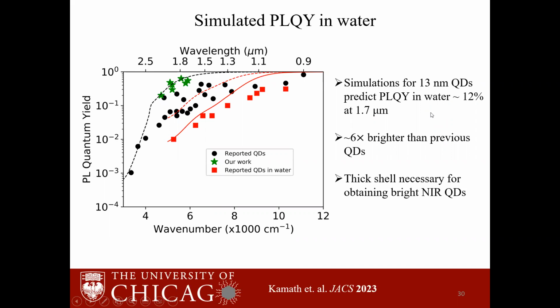And overall, our work shows that in order to obtain bright fluorophores emitting at 1.7 microns, it is necessary to grow a thick shell. And by synthetic strategies where we can grow a thicker shell, we can expect this quantum yield to reach much higher. And this has a lot of potential for bioimaging.